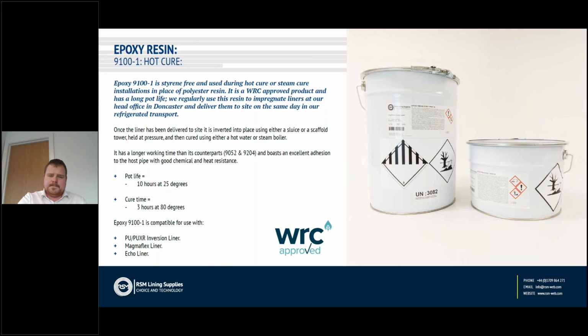Moving on to the most popular epoxy product in our range. RSM are the first people to have an epoxy resin WRC approved back in 2010. And the 9100-1 is that product. It's a specially formulated unfilled epoxy resin, which gives us a long working time and excellent heat resistance, in excess of 80 degrees if post-cured for 5 hours at between 80 and 90 degrees using hot water or steam cure.